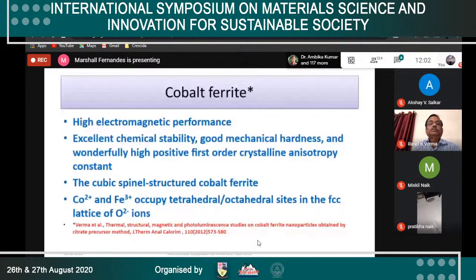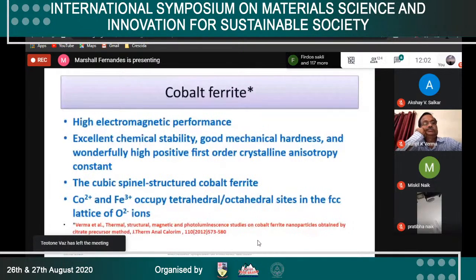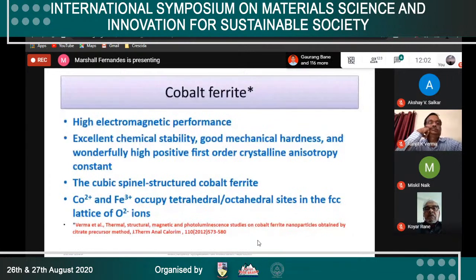It has high electromagnetic performance. It has excellent chemical stability, good mechanical hardness, and a wonderful high positive first order crystalline anisotropy constant. So this makes it technologically very important. The cobalt ferrite prepared by the citrate precursor method has cubic spinel structure, and in this structure the cobalt 2+ and iron 3+ occupy tetrahedral and octahedral sites in a face-centered cubic lattice of oxide ions.